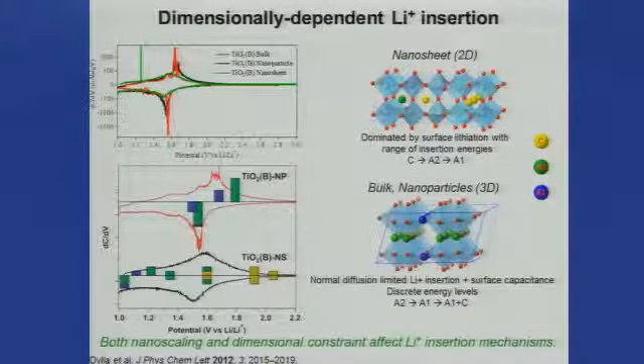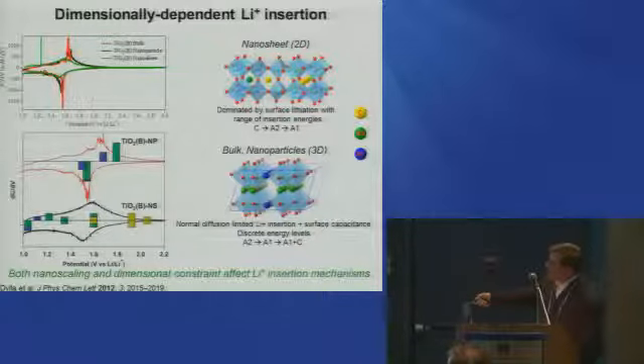And what we found in this work is, what we're doing here is galvanostatic cycling. That's basically monitoring the change in voltage as we titrate at fixed current a certain amount of charge. And if you take the derivative of that with regards to the IV curve, what you get is a differential capacity plot. This is the integrated charge with respect to the change in potential. And so what's plotted here is the lithiation going in this direction, going down, and the delithiation. And at this particular time when we did this work, it wasn't understood why you get different staging of the lithium insertion into this particular material.